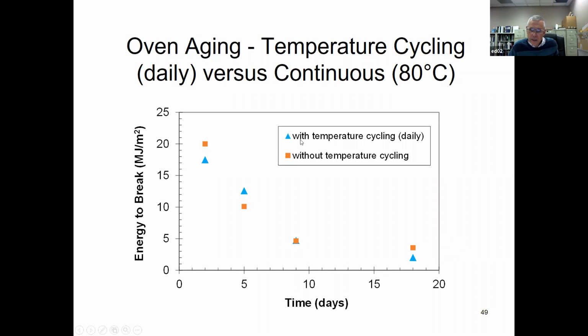With temperature cycling means every day it comes out of the oven. So it's in the oven for 1 day, out of the oven for 1 day, in the oven for 1 day, out of the oven. So it's an 18-day experiment to generate a nine day with temperature cycling. And we hypothesized that with temperature cycling it would age faster, because you're forming peroxides, and then you put it back in the oven, the peroxides will quickly break down.